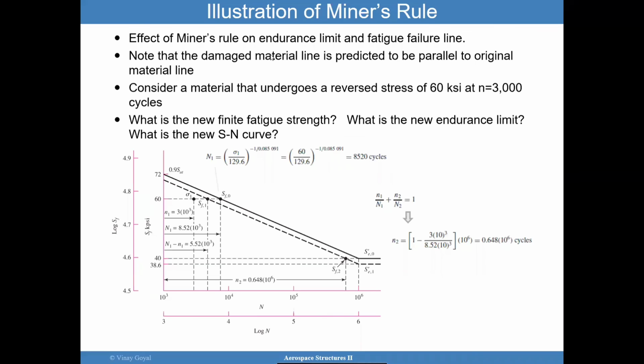Okay, so what's going on? At 60 KSI, I run 3,000 cycles. At 60 KSI, the question is how many cycles to failure? So I go to 60, hit this line, which comes from test data, and then I go down here and say, okay, that's 8,500 cycles or so. So that's what comes out here. If I use Miner's rule, I can figure out how many cycles I have remaining for this problem. So then I have N1, which is 3,000 cycles, and capital N1, which is 8,500 cycles.